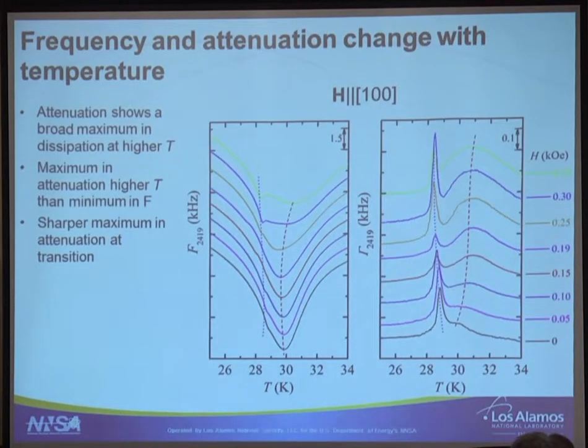Now, this is with magnetic field, and we do 2 types of measurements. I'm basically showing the tracking of one of the frequencies as a function of temperature, and the other thing that I'm showing here is the attenuation. As I said, the attenuation is basically how wide the resonance peak is. The wider the resonance, the more the attenuation. If you have a piece of epoxy or a piece of plastic, this will not resonate, or the resonance will be really, really wide. And that means that you have some sort of absorption of your sound.